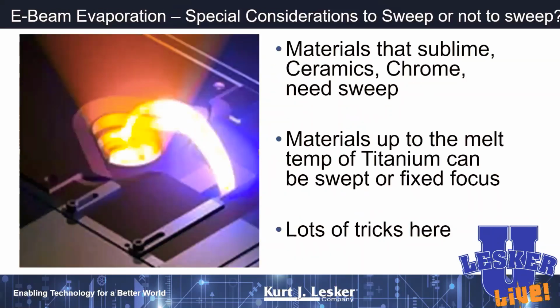Question here is, do you want to sweep the beam around? So here's an image done with an optical filter, so you can see this E-beam hitting your source, and you can see the flux coming off there. The question is, do you want to move that beam around during deposition? If you've got something which does not have great thermal conductivity, like a ceramic, or maybe metal targets that are made from powders like chrome, you may want to sweep the beam around. If you've got things which have better thermal conductivity, like titanium, maybe you don't necessarily need to sweep the beam.